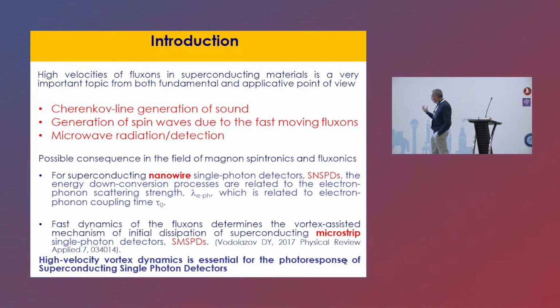The main important point is related to the electron-phonon scattering strength, which is related to the electron-phonon coupling time tau 0. This is not directly connected to the quasi-particle relaxation time that we detect from the instabilities in the IV characteristics, but the scaling between these two quantities is quite robust, in the sense that low values of the inelastic scattering time will typically give a low electron-phonon coupling time in the material.